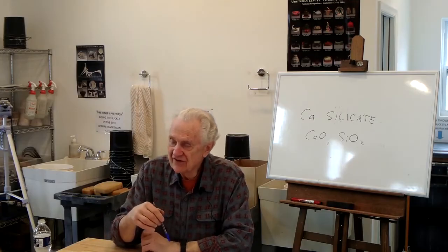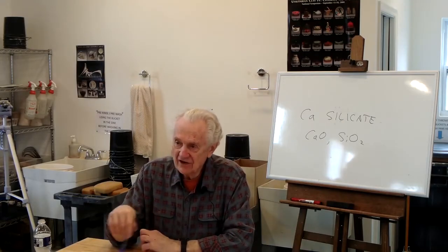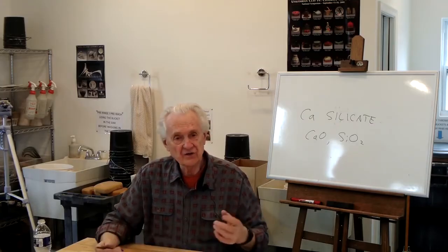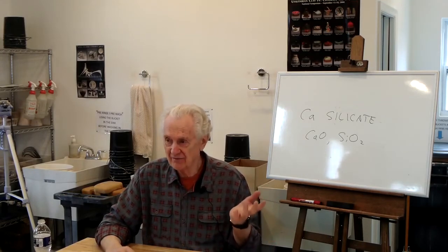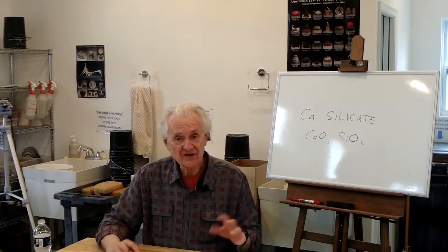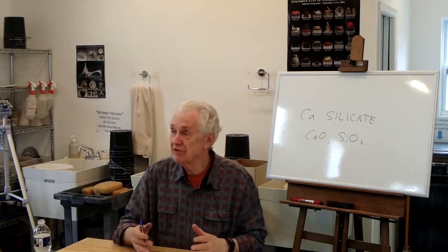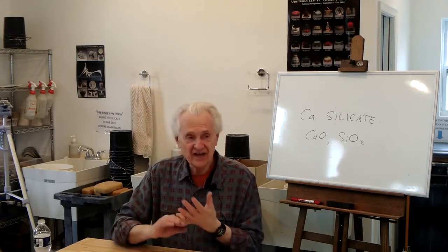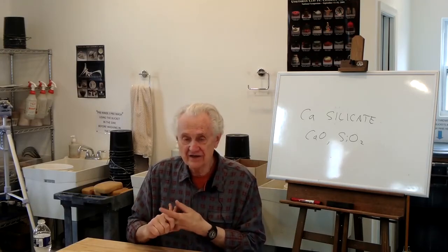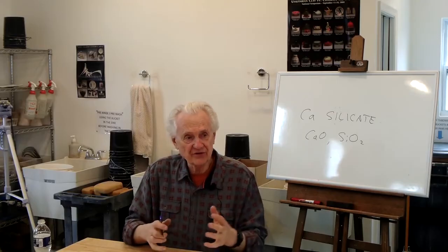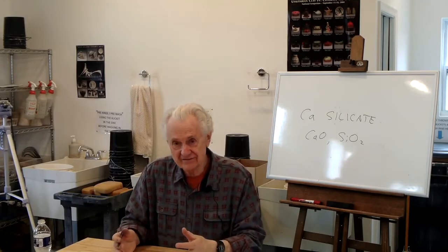So this was used extensively in the earlier days of pottery in this country and all over the world, because all you need to do is take the clay, mix it with water, make a slip out of it, put it on your pot, fire your pot to cone 10, and you have this beautiful chocolate brown, mahogany brown glaze. That clay itself is a very impure clay, so it contains a lot of silica, a lot of the fluxes, and all the alumina you need in just the right proportions to make a perfect cone 10 glaze.